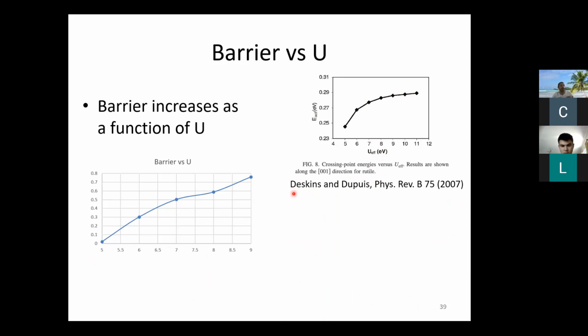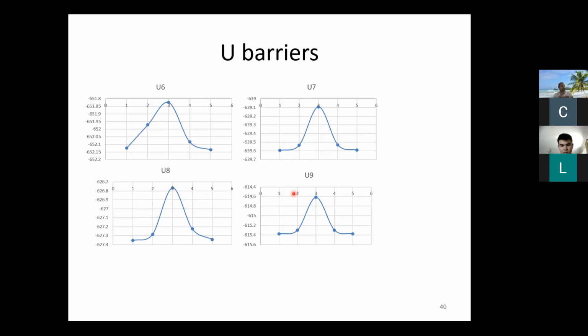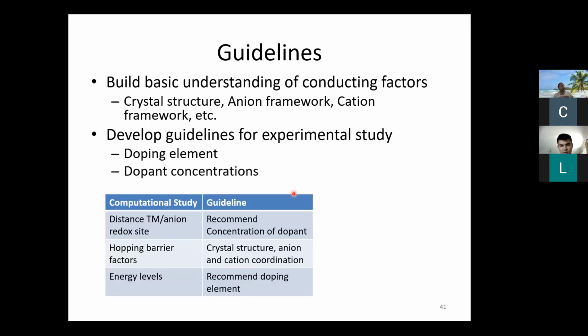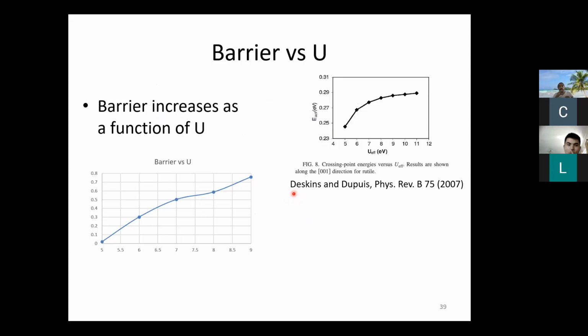But we don't want just a random dependency on this. We want to make sure this is more ab initio, where we're starting from a fundamental level, and we leave it at that. Here's just another barrier to that. Right now I'm going through the literature to find out which are the appropriate values to use, and there are a few different methods to try. One fault of DFT plus U is that you can't necessarily just match it to the band gap like you can for some other methods, because certain parameters still don't fall appropriately.